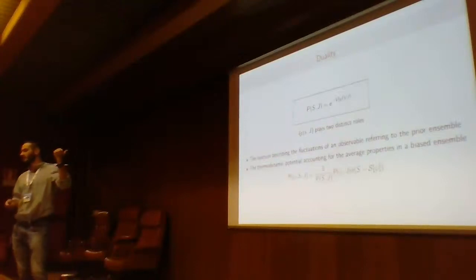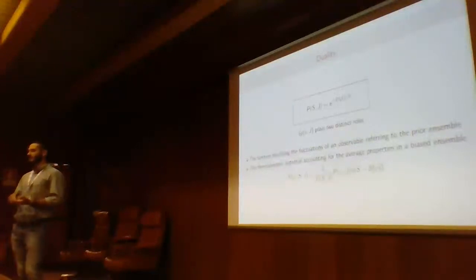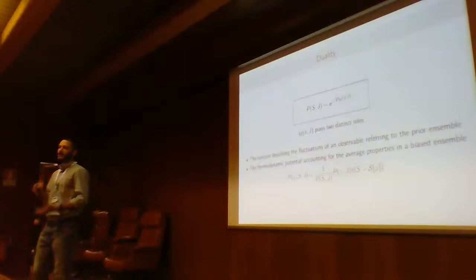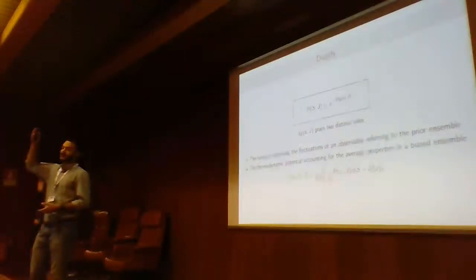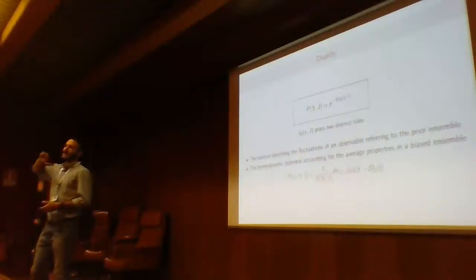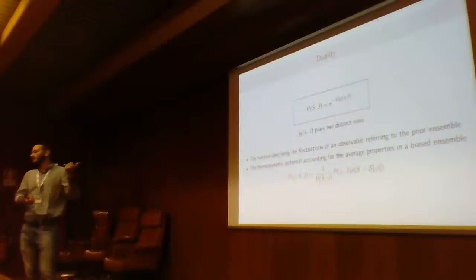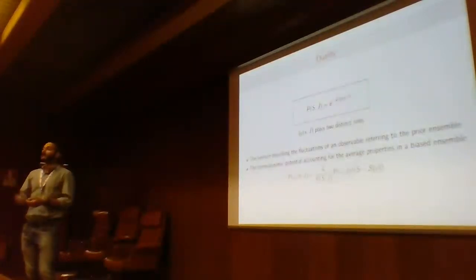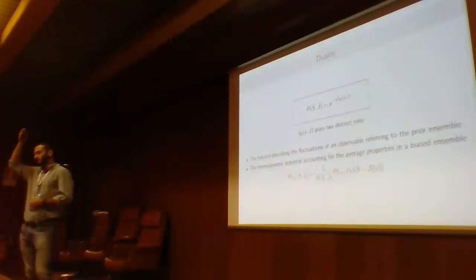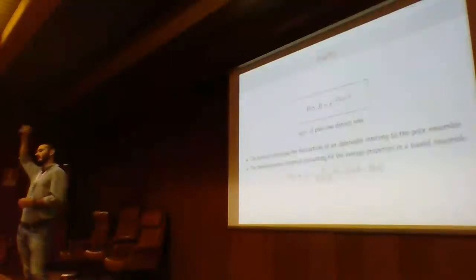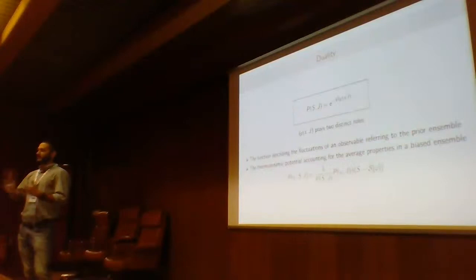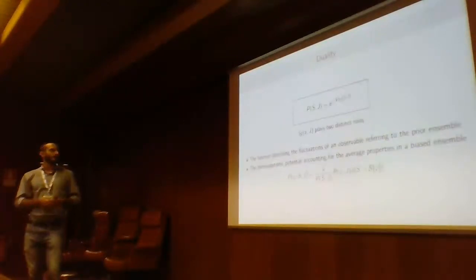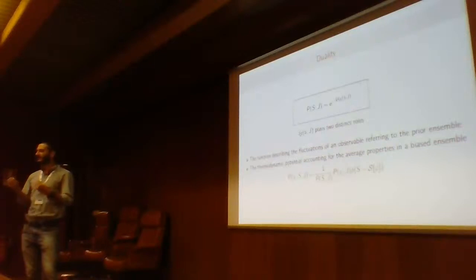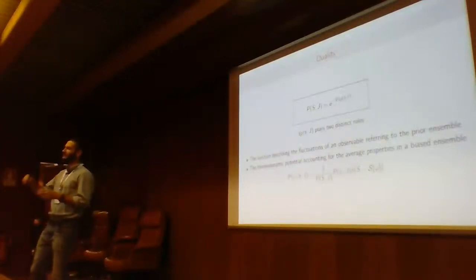So there is this duality, and one can exploit tools from equilibrium statistical mechanics to study things. Indeed, we chose that observable in this case because the dual model to this is a well-known model. It's the spherical model of Berlin-Kac describing the magnet. And this model undergoes a phase transition from paramagnetic to ferromagnetic. And this transition is strictly related to the condensation transition we saw in the fluctuations of the other model, and also in the dynamics. Indeed, when the magnet gets quenched from a temperature greater than Tc to low temperature, it undergoes coarsening, and the size of the fluctuations grows algebraically. And we recover something that resembles the more involved behavior that fluctuations with condensation have during the non-equilibrium dynamics.